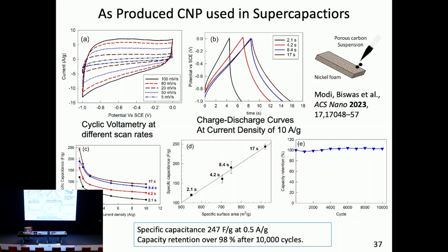These carbon nanoparticles are tremendous for use in supercapacitors, and you want to compare it to the conventional materials used. And of course, you would now make a suspension and make a film, put it into a 3-electrode system to measure the capacitance, and these are all cyclic voltammetry, charge, discharge, and you see that you can get a rather high capacity which is maintained.